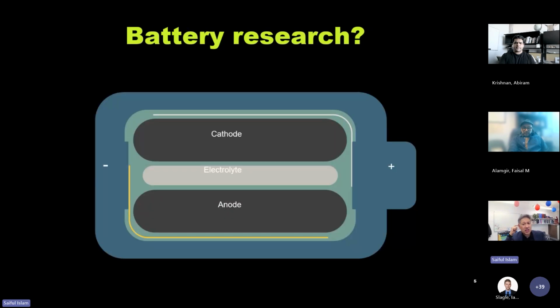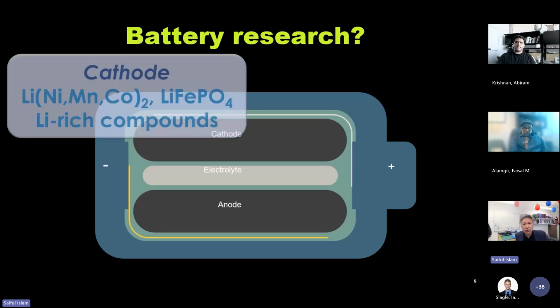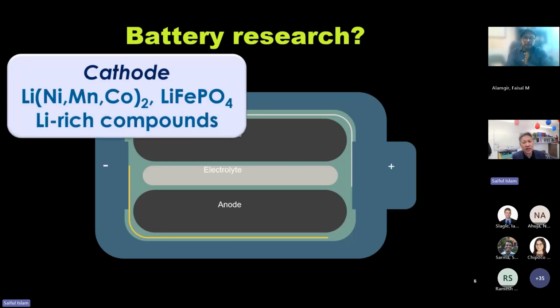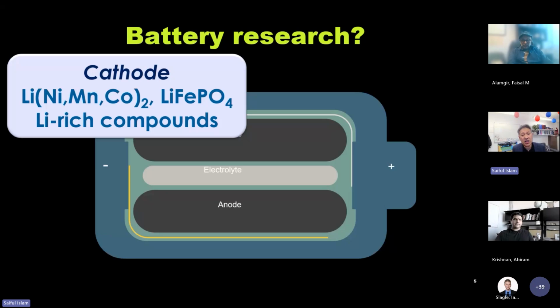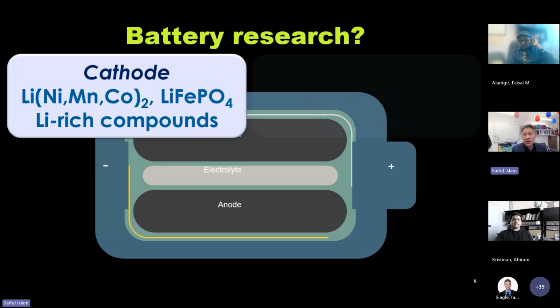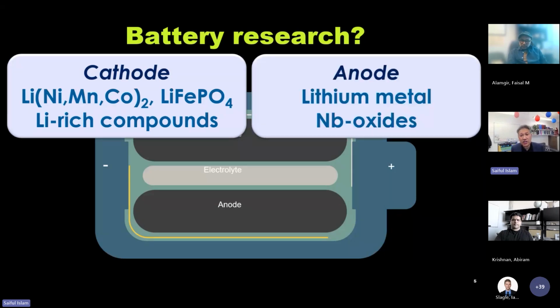So what is the battery research in the material space? It falls into different areas. In the positive electrode, the cathode space, a lot of research is looking at NMC type materials, nickel, manganese, cobalt, particularly nickel rich. Then there's an increasing interest in lithium iron phosphate, and an area that we're looking at, lithium rich compounds. On the negative electrode side, the anode side, there's work looking at obviously carbon composites, but looking at lithium metal and niobium oxides.